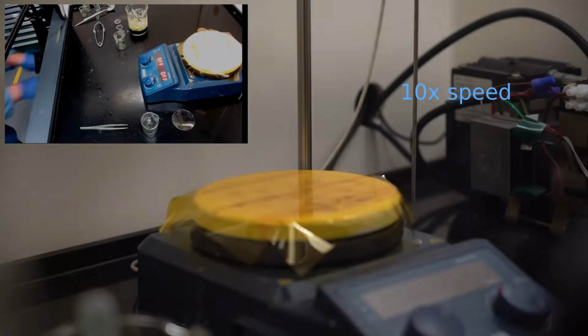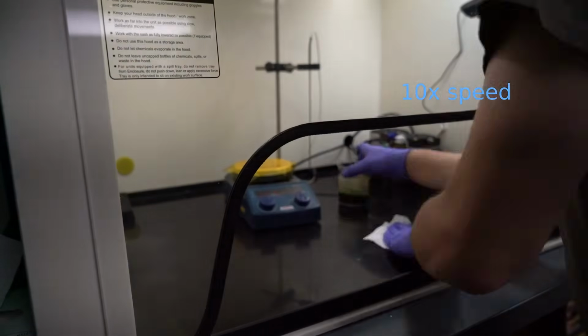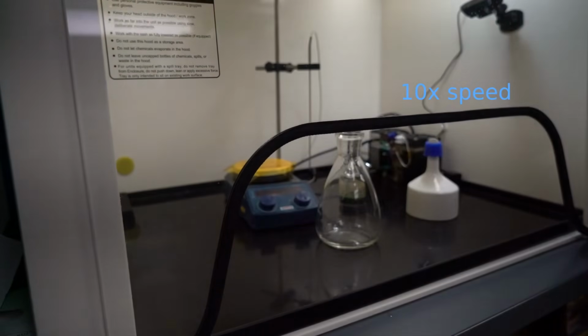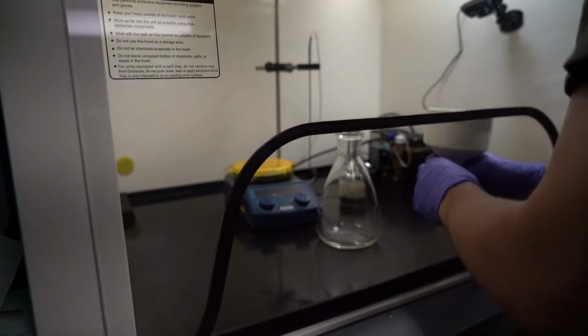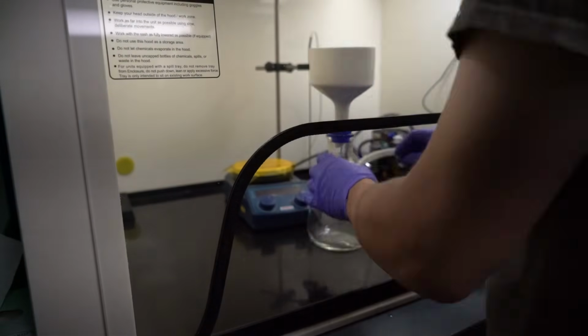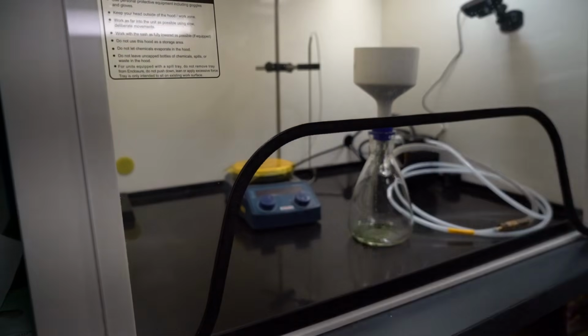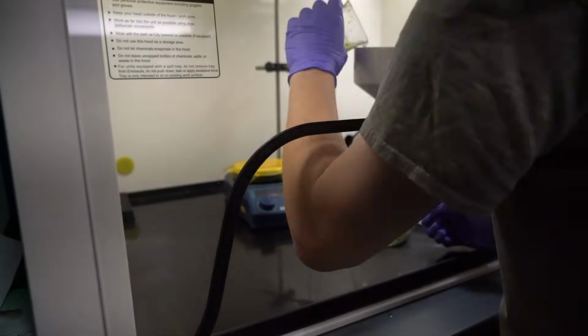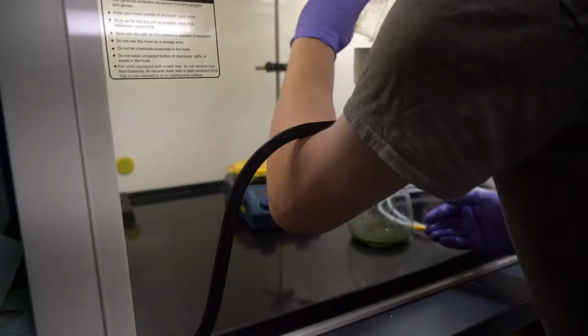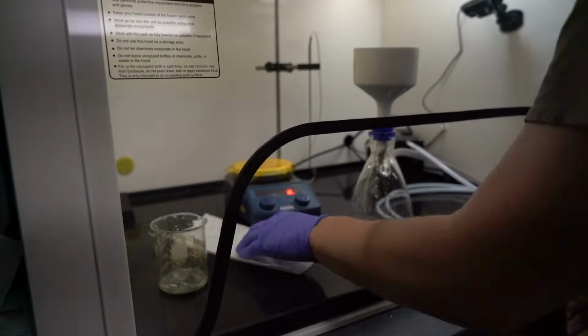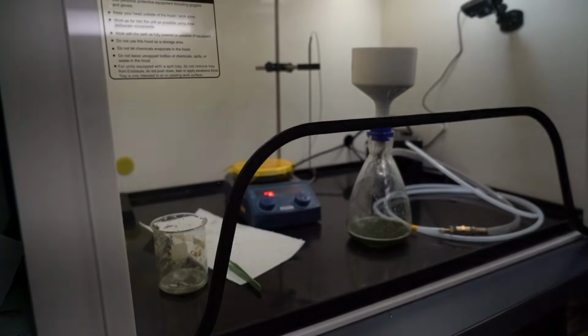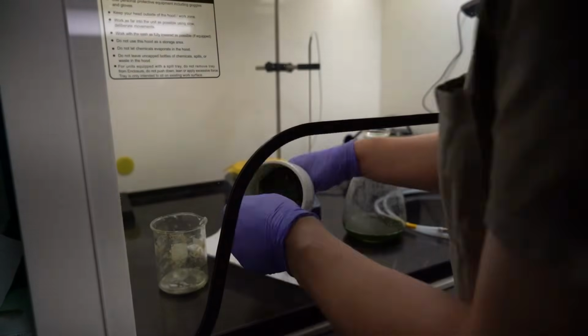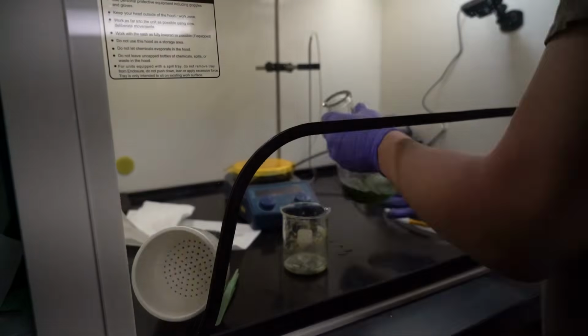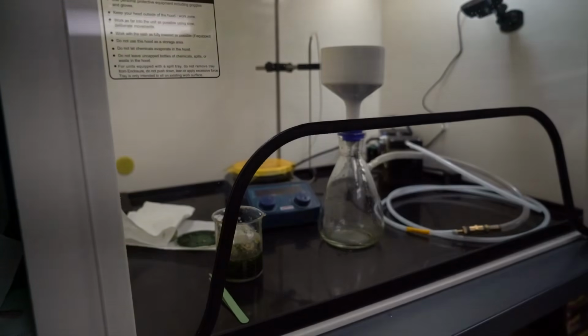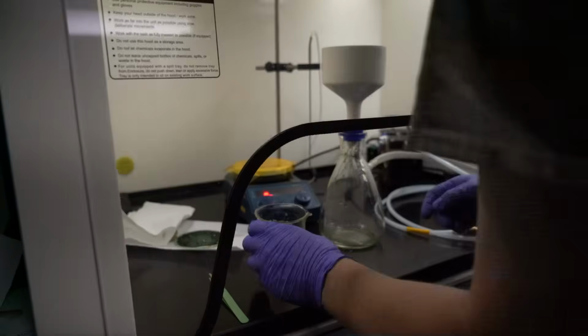And so now I'm just taking the last couple of samples off and cleaning them. And now everything is done, and I'm deconning the hood. You'll see the only thing left is the waste beaker, and now I'm just setting it up for filtration to filter off as much of the copper carbonate as I can. A good chunk of it comes out as particulates. Some will stay in solution because it either didn't completely react or the pH was not quite perfect to precipitate it. So that gets put in a separate waste jar and just held onto until I can take it to a disposal site.